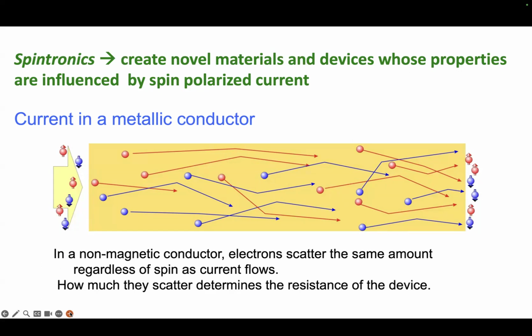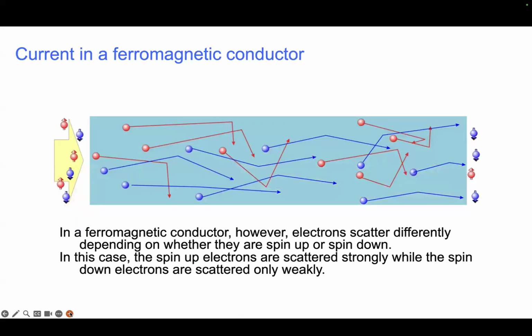Copper is a non-magnetic metal, and if you introduce current from a battery on the left-hand side, the current will be carried equally by spin up and spin down electrons. This is what happens. However, if you have a magnetic material, then it turns out the magnetization breaks time reversal symmetry, and moreover means that electrons with spin up and spin down are scattered at different rates from these magnetic moments. And this leads to, in some magnetic materials, the fact that the current is innately spin polarized.